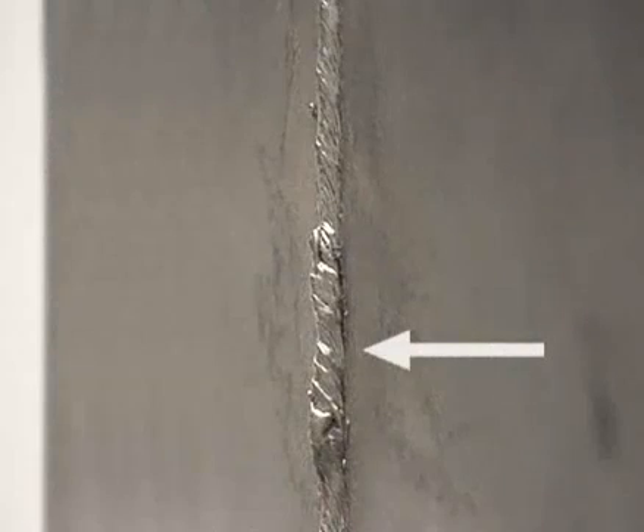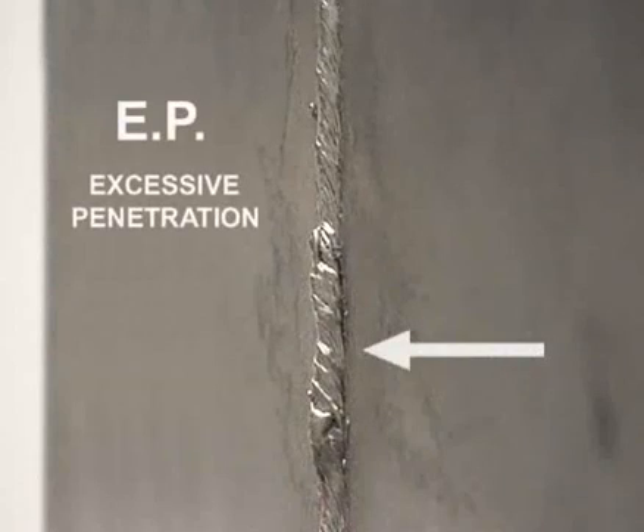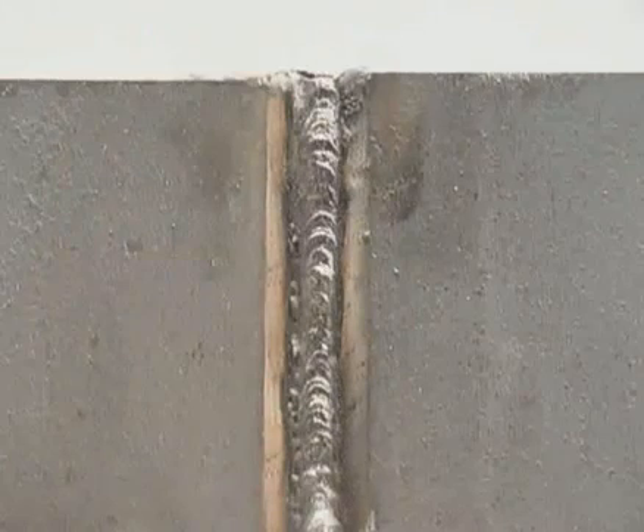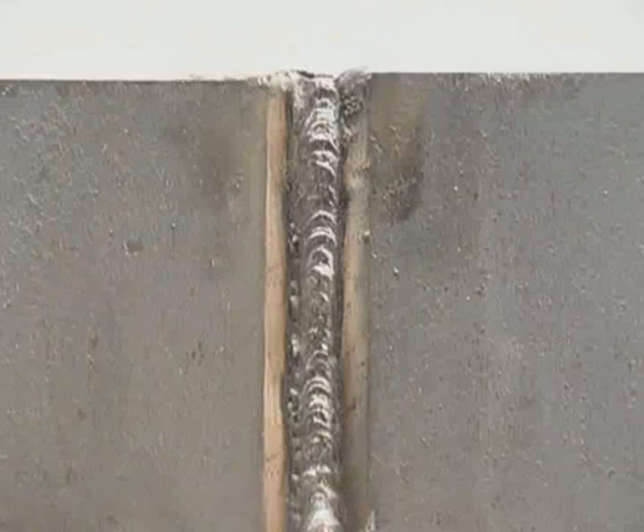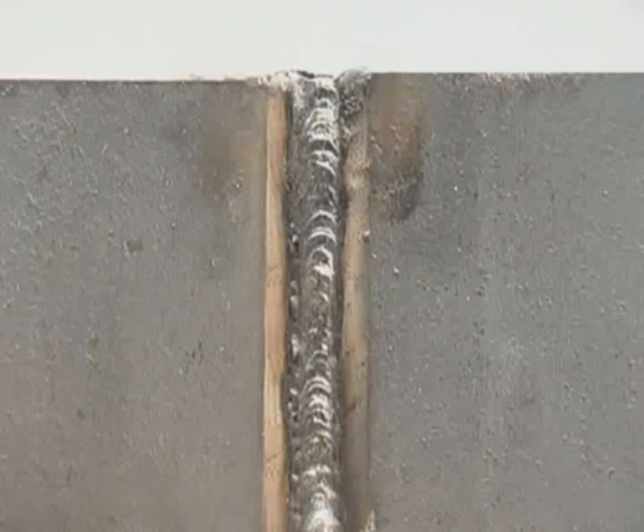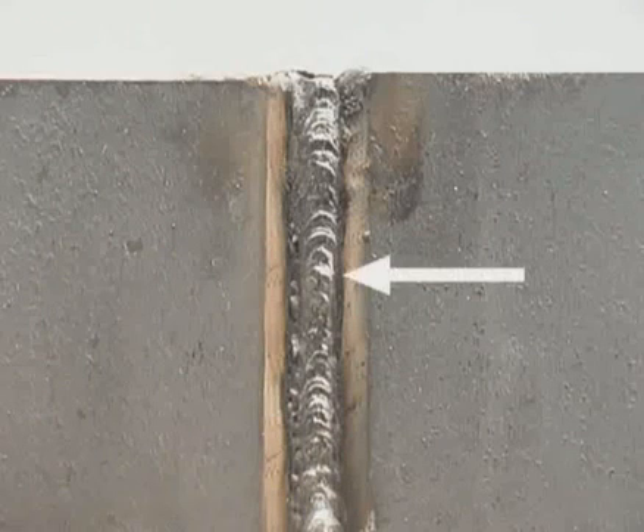The bead stacks up on the backside, causing excessive penetration. On the front side, because the rod was jammed right down against the metal, the bead will crown and undercut along both sides. Grind this out to avoid trapping slag. The metal will be thin from grinding, so you need to run another bead called a hot pass to add a little more metal and burn out any slag left behind.